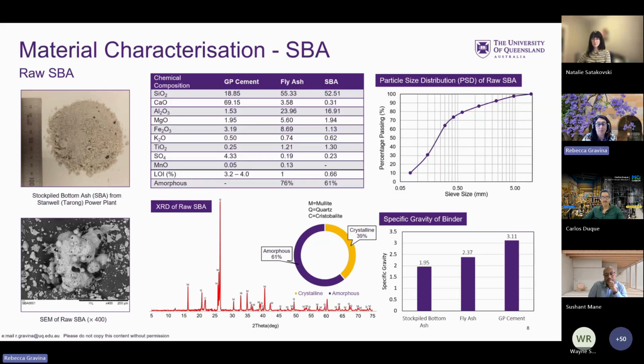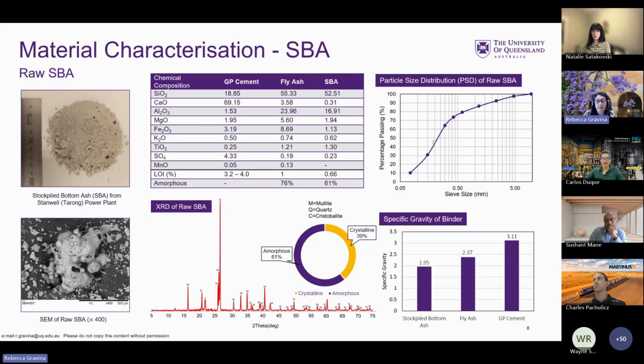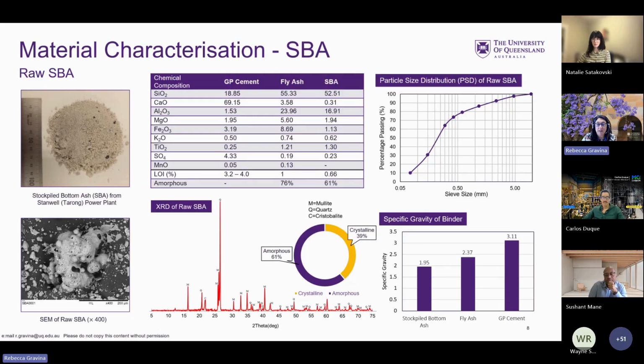However, the particle size of the stockpile bottom ash is much larger, as you can see from this top right-hand graph, but the size range is a little bit closer to the sand. And so having that particle size a bit larger in the stockpile bottom ash led us to the next phase: what do we do in terms of potentially grinding the stockpile bottom ash using a ball mill.